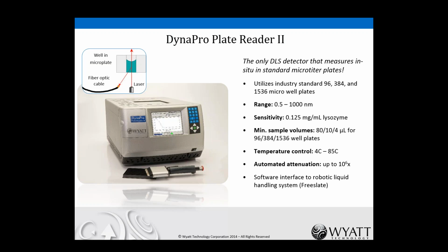You can ramp the temperature of this plate in order to assess thermal behavior. For instance, the temperature of unfolding or the onset of aggregation. And regardless of having a wide range of samples in your plate, some of which may be very pure and some of which may be heavily aggregated or full of particulates, you don't have to worry about setting the laser intensity. It automatically attenuates by up to a factor of 1,000,000.